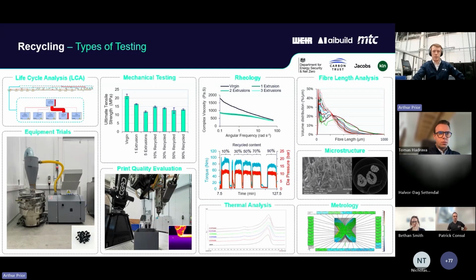Controlling particle size distribution is really important. So this requires, in our experience, the material to be sieved after shredding and granulation. And if you can control that particle size distribution, then printing directly using regrind is feasible with just some minor equipment modifications.